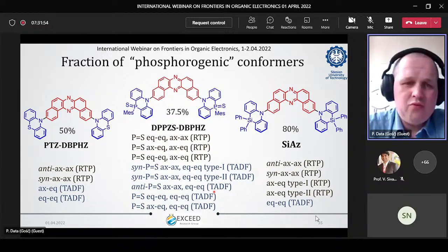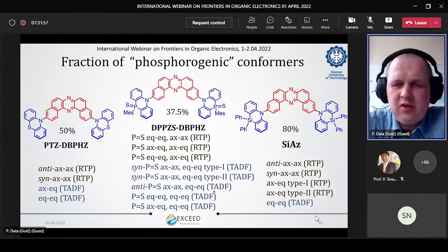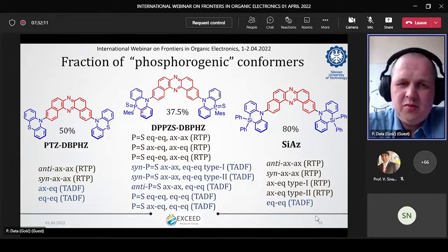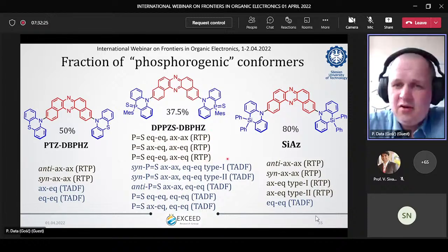So as follow-up work, we decided to focus on how to tailor molecules which will have more different conformers, and how those different conformers will affect our emission. In the meantime, we had molecules which had 8 different conformations, and depending on the conformation had different TADF or RTP processes. At that time, we wanted to push for more room temperature phosphorescence properties, and because of that, we decided to focus on molecules forming more mixed axial-equatorial conformations rather than equatorial.